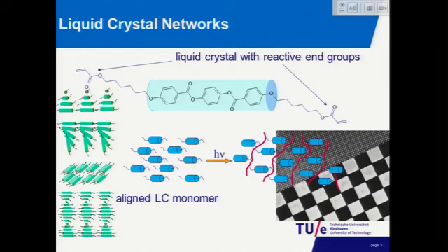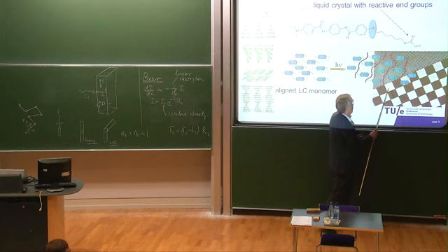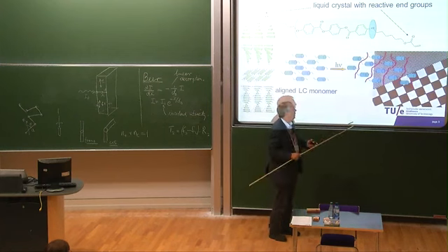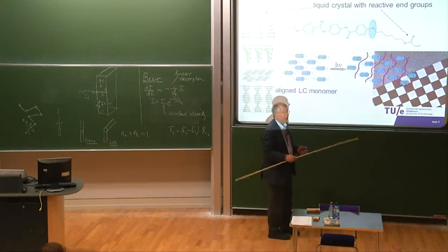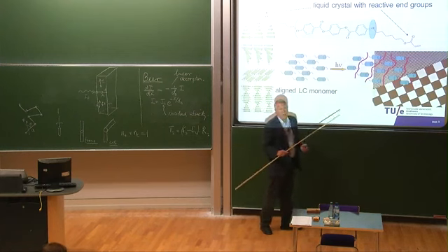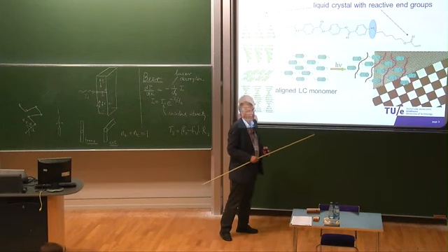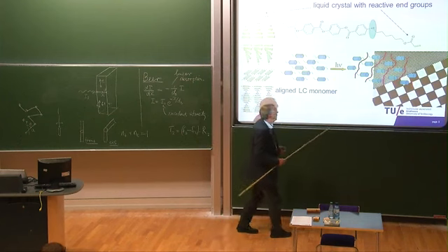And because we are using light to initiate this reaction, we can also use lithographic techniques to do it locally, just by using a mask. You locally shield the area from light. You polymerize only in the illuminated states. That orientation is frozen in, and you still have liquid in the dark states, which can be converted into another type of orientation, or can just be made isotropic by heating.